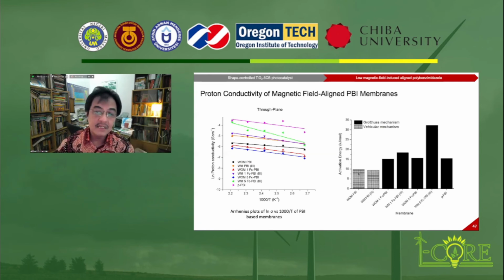This indicates that a similar proton conduction mechanism dominates in both cases here, which is known as the vehicular mechanism. In addition, the higher activation energy of the polymer sample, around 15 kilojoule per mole and more than 15 kilojoule per mole here, signifies that the Grotthuss mechanism is the dominant proton conduction mechanism of the membrane. We know that the Grotthuss mechanism exhibits activation energy in the range of 14 to 40 kilojoule per mole.